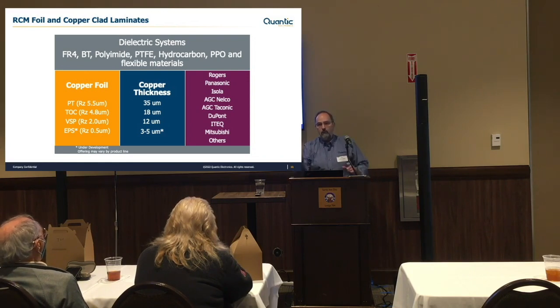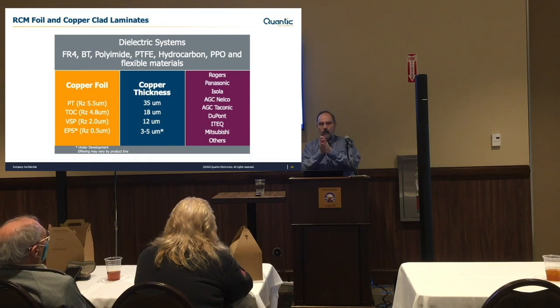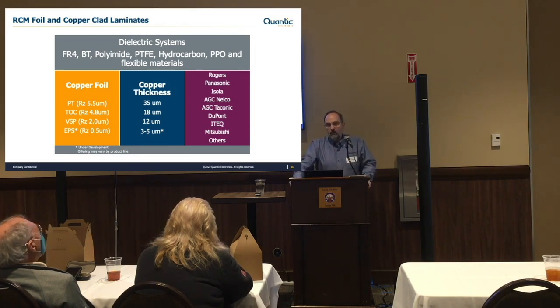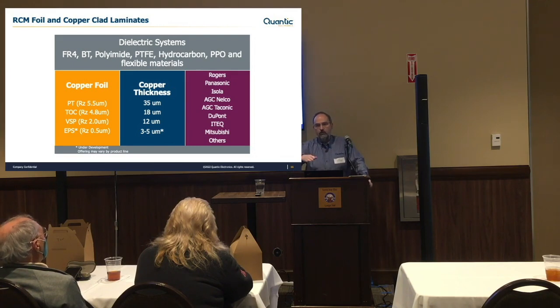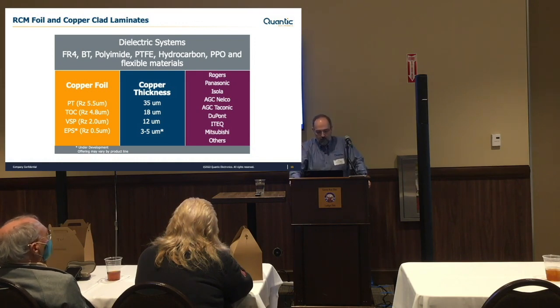So what happens is they basically have a copper carrier, and then there's a release layer, and then they plate 3 to 5 microns. Actually, can go lower than that. They go down to 1.5 microns. And then when you laminate it to your base material, you then peel the carrier off. And people want to do that for semi-additive processing. So if you start with a very thin base of copper, then you can put your photoresist down and plate up, and you can get much finer lines and spaces doing it that way. So there's some people interested in that, and we're developing on putting our resistor layer now on that 3 to 5 micron copper.